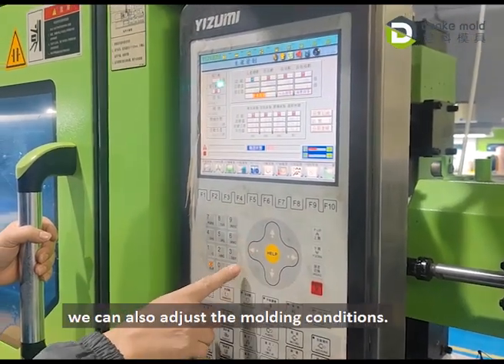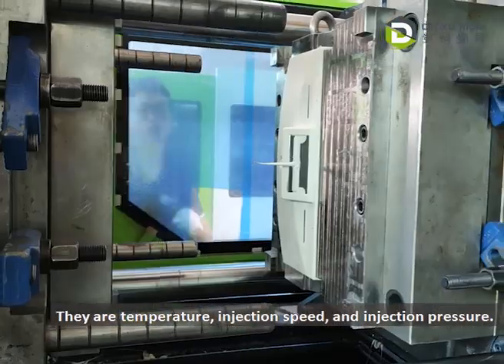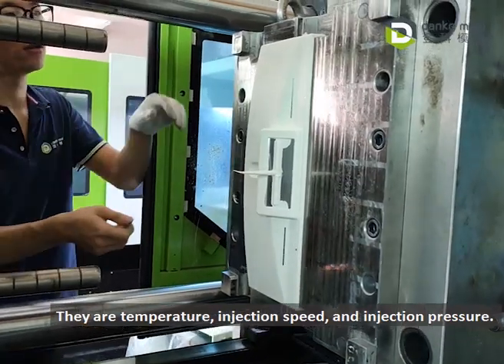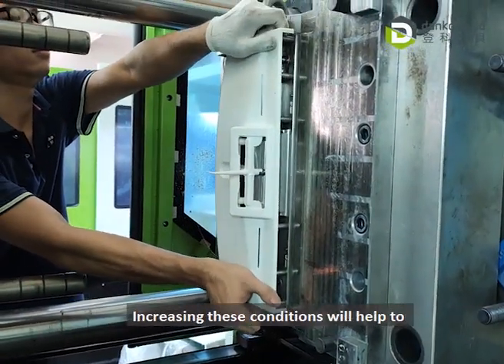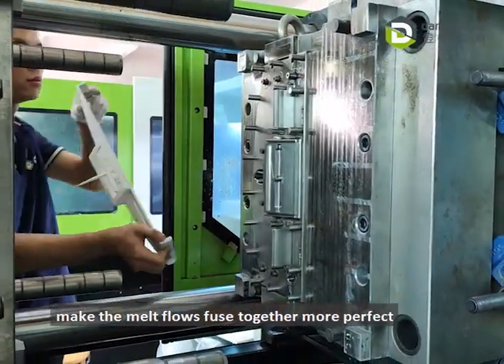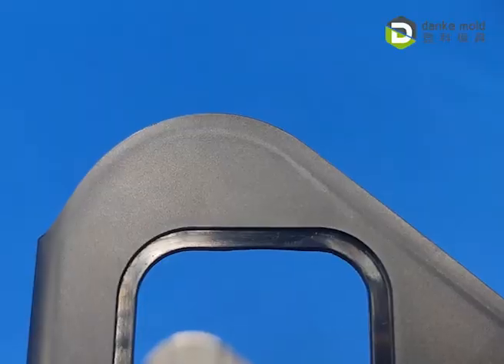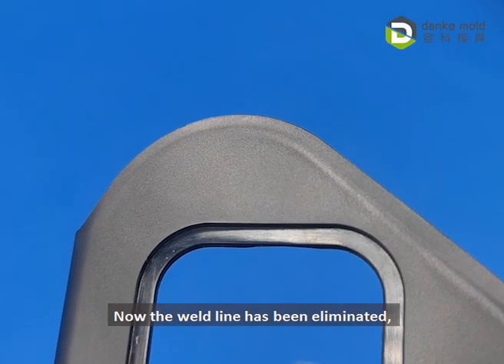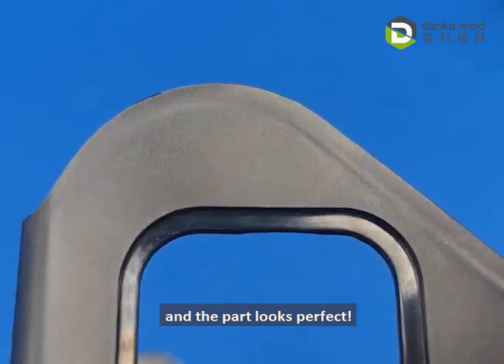Besides, we can also adjust the molding conditions. They are temperature, injection speed, and injection pressure. Increasing these conditions will help make the melt flows fuse together more perfectly. Now the weld line has been eliminated, and the part looks perfect.